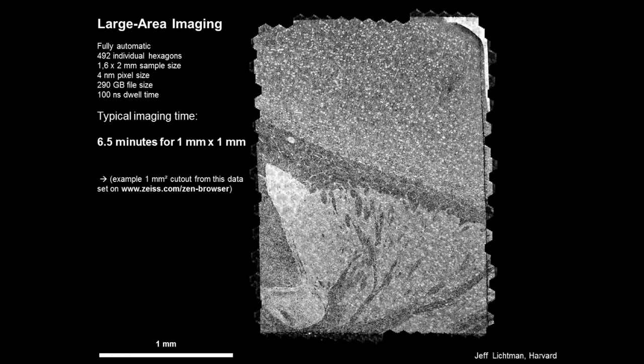Now, this is a data set that can be taken fully automatically. It's about 300 gigabytes in data size. And the section has an area of a little bit more than 3 square millimeters. Typically, we can image such a section in, let's say, 15 to 20 minutes. 1 square millimeter can typically be imaged in about 6.5 minutes. It depends a little bit on the actual imaging parameters and on the sample properties, but something between 5 and 10 minutes is a typical imaging time.